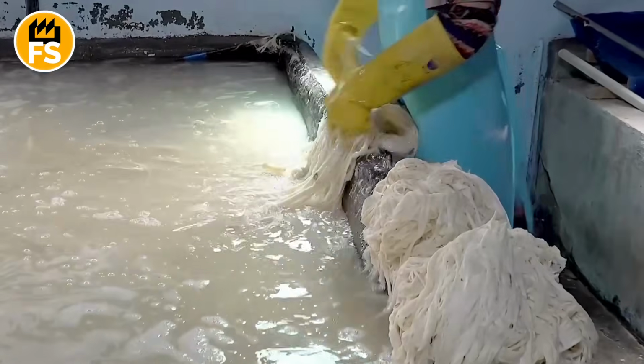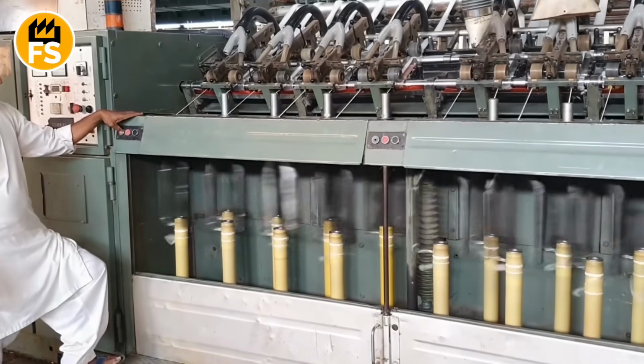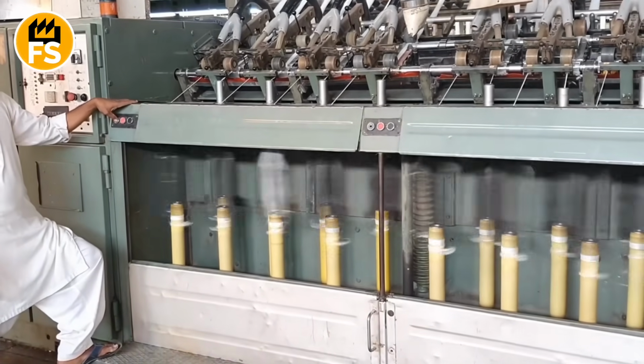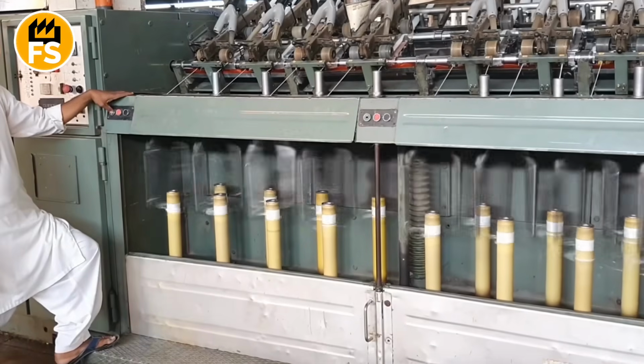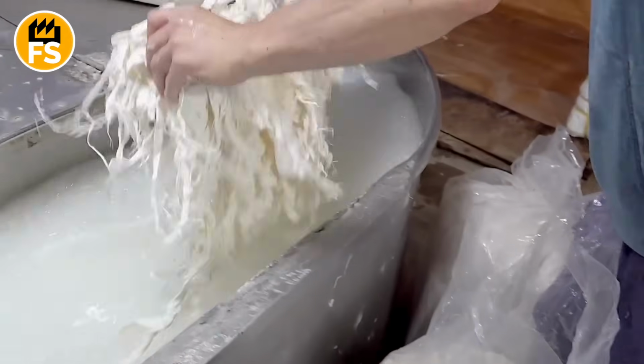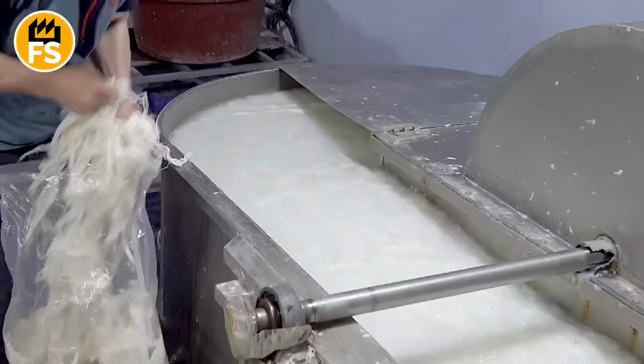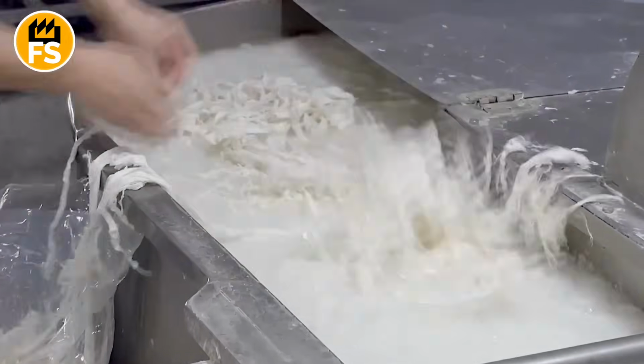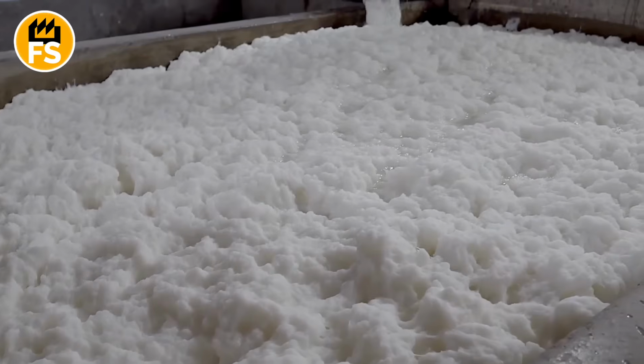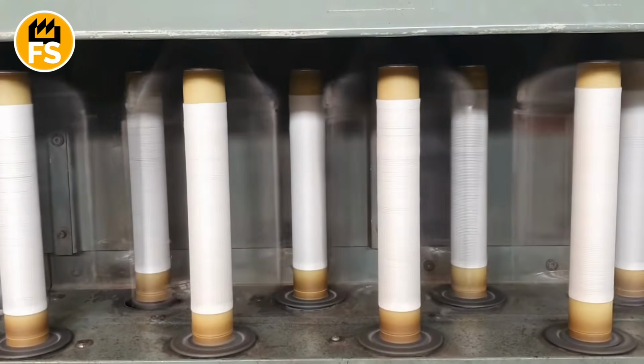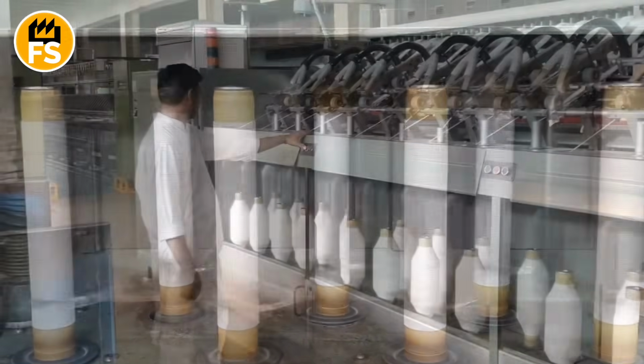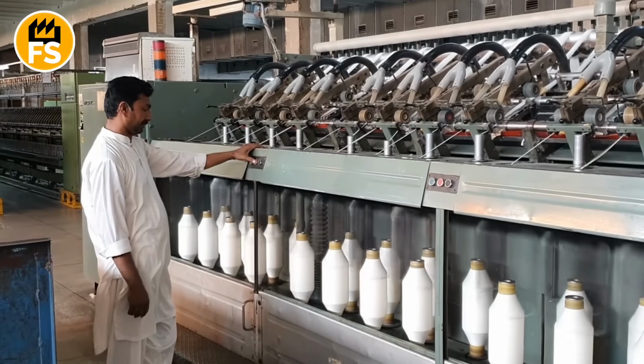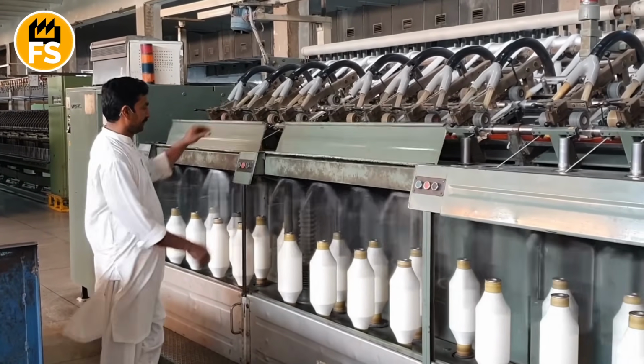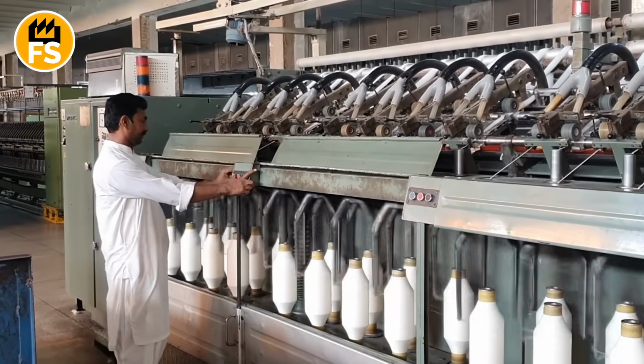What's left is a sticky, dense gel. This gel is then forced through microscopic holes in a metal plate called a spinneret, like a giant molecular meat grinder. On the other side emerge ultra-fine, continuous threads. These threads drop into a bath of another chemical, usually sulfuric acid, which instantly solidifies them. Now we have silky, shiny fiber, bamboo viscose. It's washed, dried, and spun into yarn, which is then woven into incredibly soft, breathable, and hypoallergenic fabric.